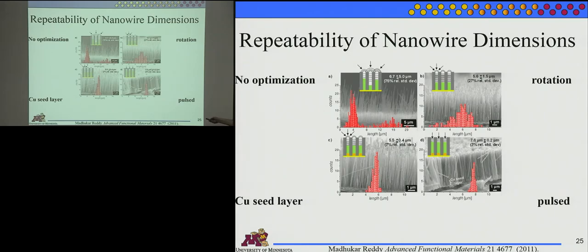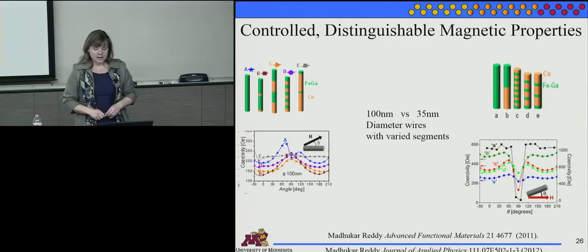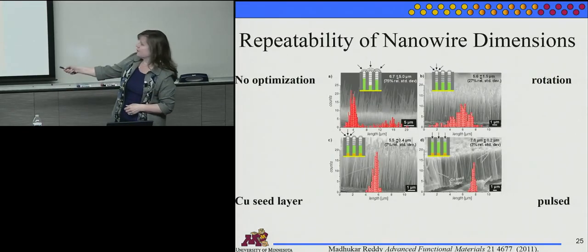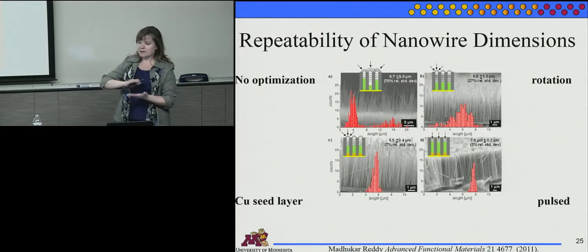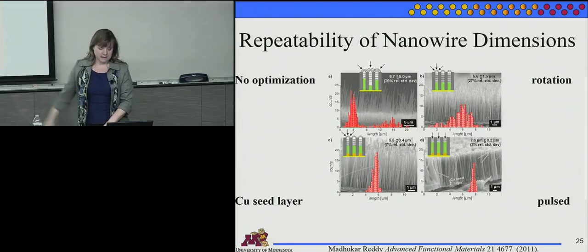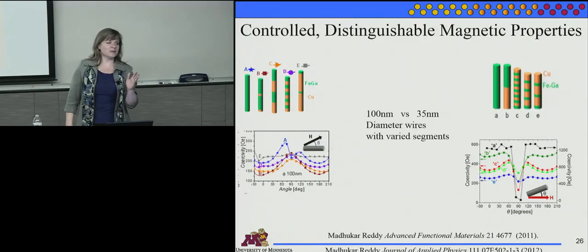So then we will go back to a trick we use almost all the time. Just put a little copper down first to make sure there's good contact between the contact film and the pores themselves. And then we get 7% standard deviation. And if you couple that with pulsing, which if you're doing layers, you're kind of pulsing anyway. But even if you're just doing a straight alloy, if you pulse it, you kind of rinse the pore out and bring in new solution a lot. And then we find 3%. I wish I had thrown in a blown out of this also, because it's just perfect for the whole thing. They're all really exactly the same length. Okay, 3%, not the same length.